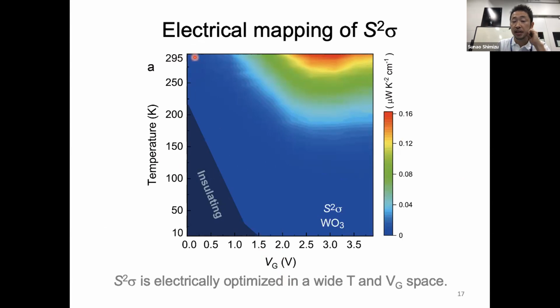So when we increase gate voltage, the power factor gradually increased, and then it showed the maximum at around 3 volt, and then started to decrease. So this data shows that we can successfully maximize or optimize the power factor of tungsten oxide thin film.